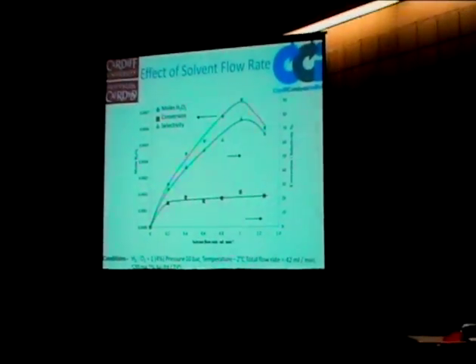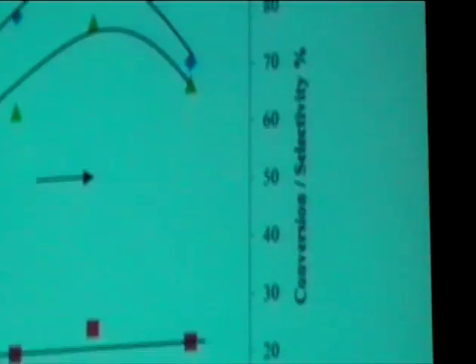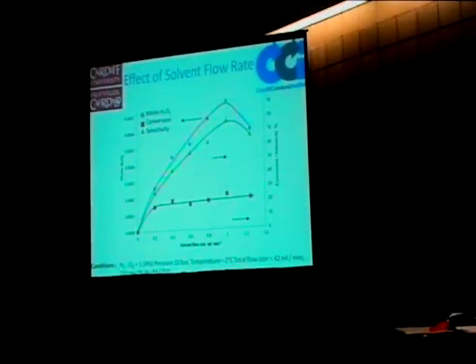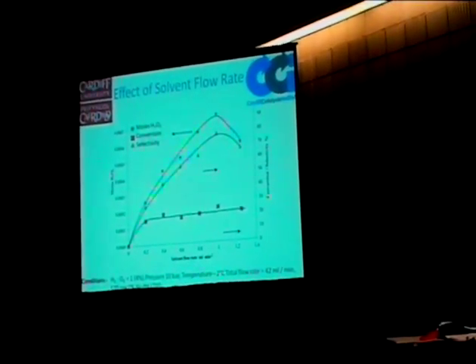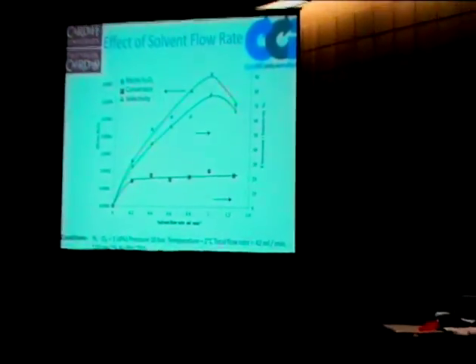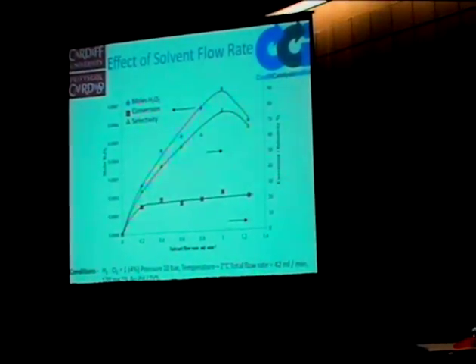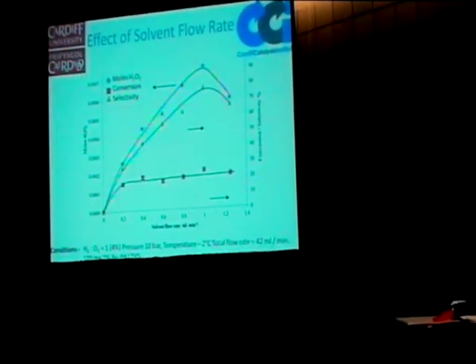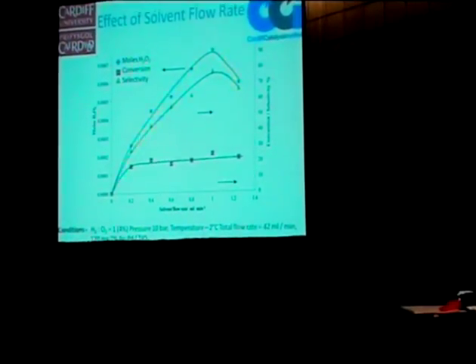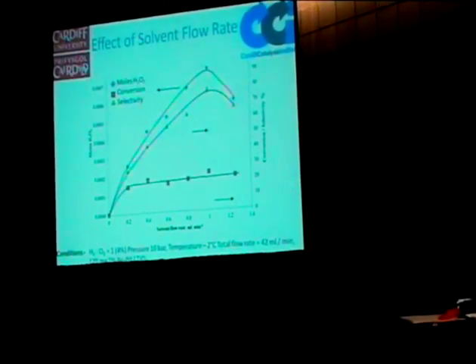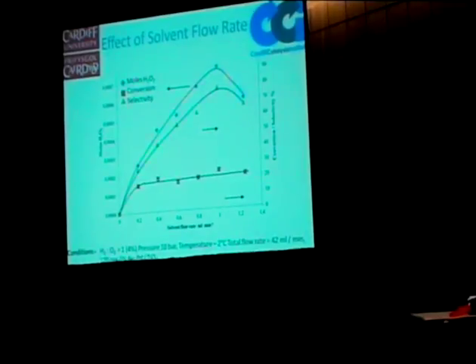So we measured the conversion and the selectivity. As we see, as the solvent flow rate increases, the number of moles of hydrogen peroxide also increases, while the conversion remains fairly steady. So the increase in the moles of hydrogen peroxide must cause an increase in the selectivity. And we explain this by saying that the more solvent in the system, the more shielded the hydrogen peroxide will be from the catalyst. So you're effectively diluting the hydrogen peroxide and slowing down the subsequent hydrogenation and decomposition reactions. And this is very high selectivity of hydrogen peroxide, around 80%.